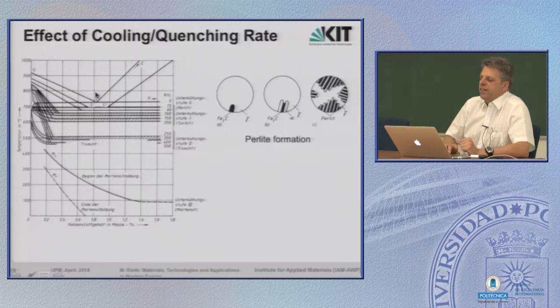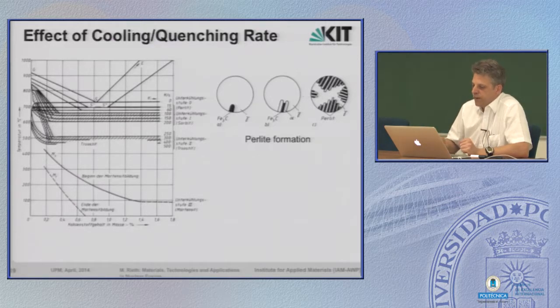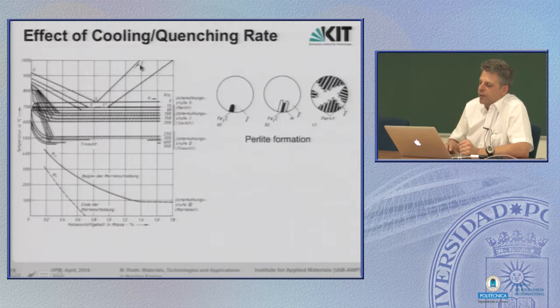If you do it very slowly, then you can rely on the phase diagram. If you do the quenching with a higher speed, then the transformation shifts with increasing speed to deeper and deeper temperatures, because you are, well, hurrying. You are too fast to have time for all the transformation. So the original equilibrium phase diagram has to be modified. All these phase lines are shifted downward towards lower temperatures.